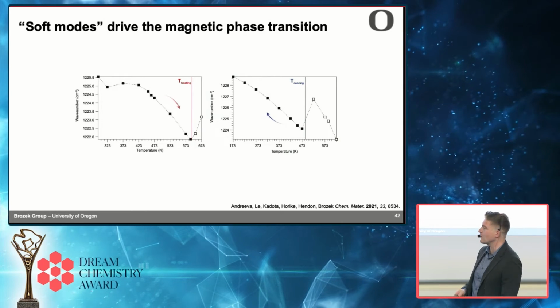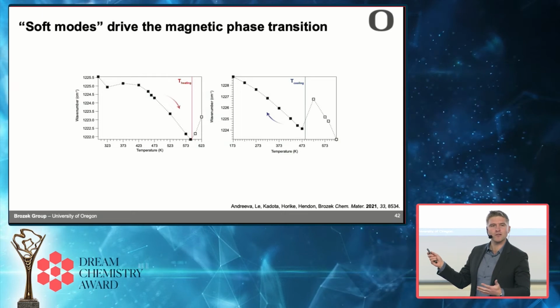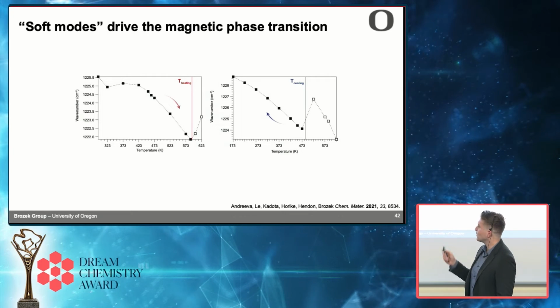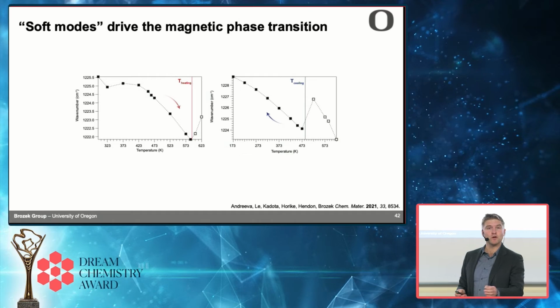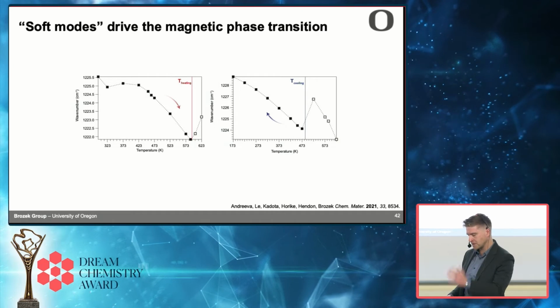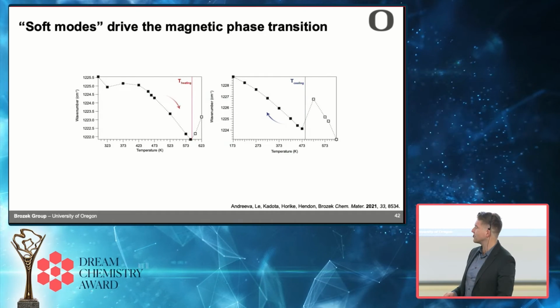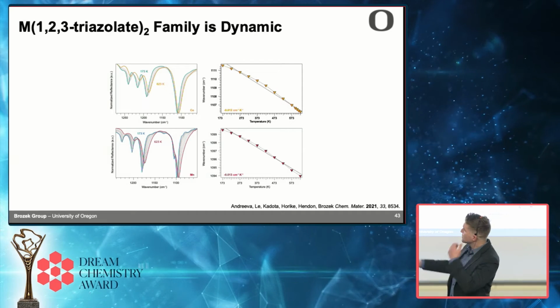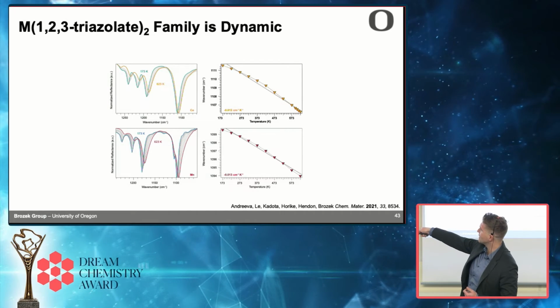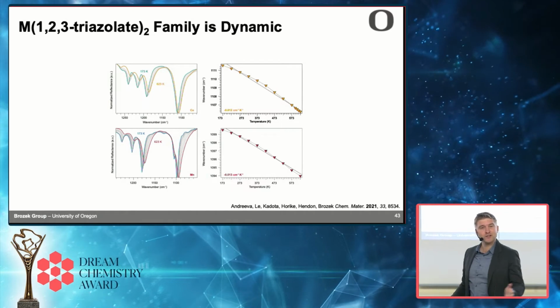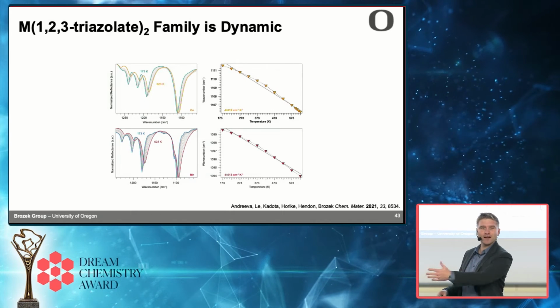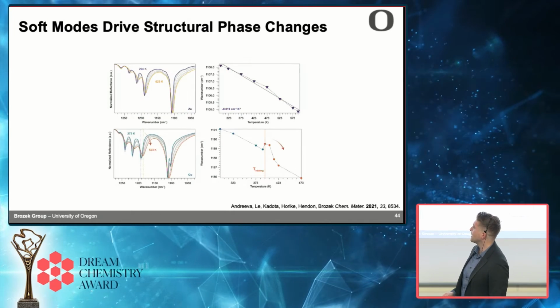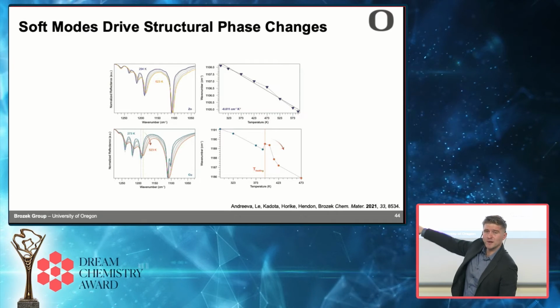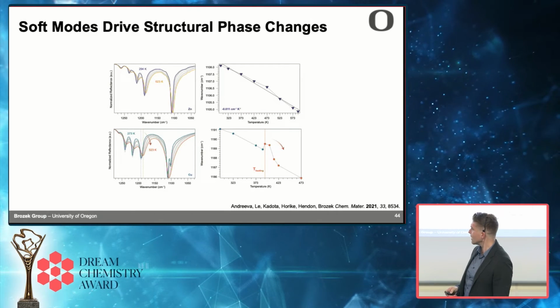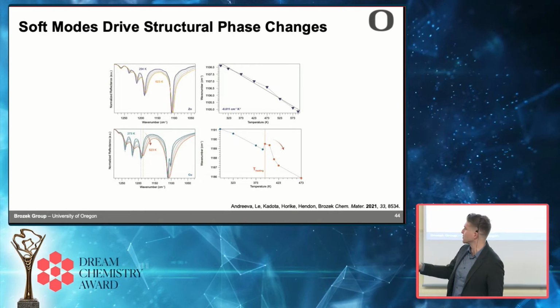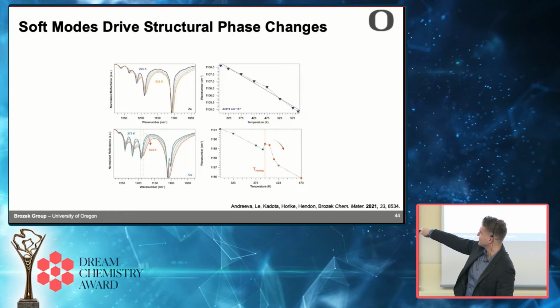Okay, so that was nice to see, and I wondered, is this really unique to this material? Well, one of the nice things about iron triazolate is it belongs to a family of isostructural materials. You can make it with zinc, manganese, cobalt, copper, etc. And when you look at those, here's the data for cobalt, here's the data for manganese. The triazolate stretches all redshift, so they have that dynamic character. Here's the data for zinc, it does it too, but they don't have that inversion. The only one that does is the copper version. There's a little baby kind of inversion here.